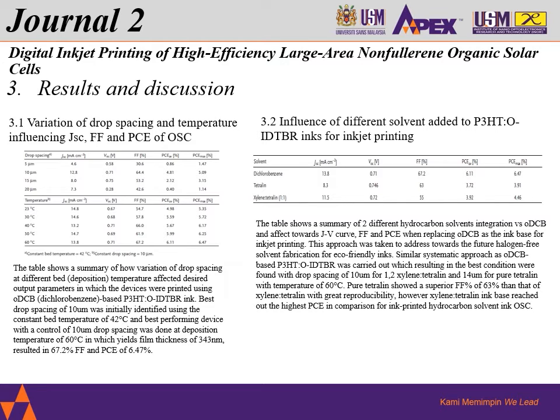This is the deposition temperature, and you can see that the highest PCE achieved was with a 10 micron drop spacing. Then subsequently, this 10 micron drop spacing is kept constant while finding out what temperature is the best for digital inkjet printing. It varies from room temperature up to 60 degrees Celsius. With 10 micron constant drop spacing, the maximum PCE achieved here is 6.47%, which was done at 60 degrees Celsius. And it also yields up to 67.2% fill factor across all the temperatures.